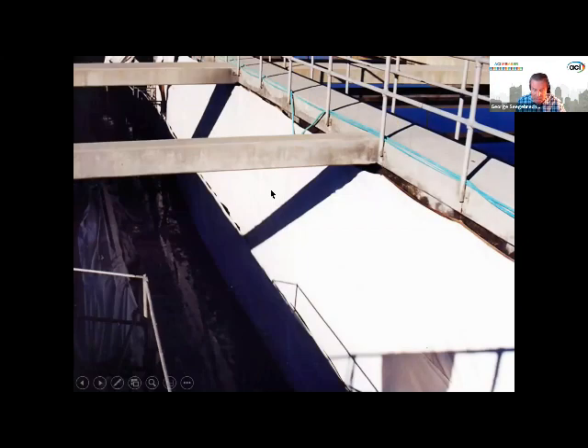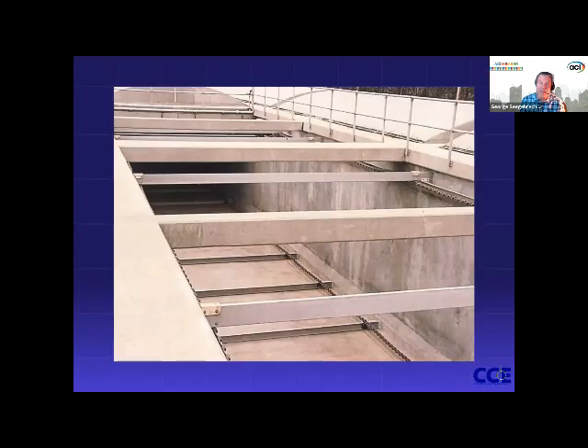I am sorry, I'm getting close to my time, but I'm going to get these last couple in. Ingenuity of curing here by this shotcrete contractor on this project. He basically took burlap and kind of made a shower curtain out of it by hanging it vertically, very tight to the wall, with soaker hoses, keeping an air gap of about an inch, and he kept the wetness on there very, very nicely. Appearance wasn't an issue because it's just going to be a tank for poop. In fact, this project won an ICRI, International Concrete Repair Institute Repair Award. I won't even tell you the year that happened.